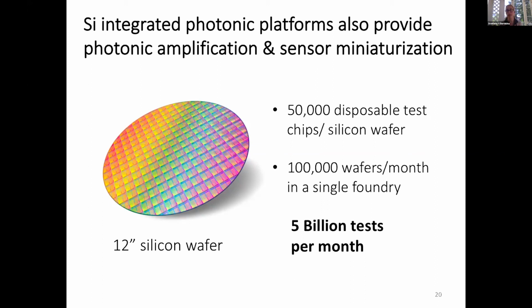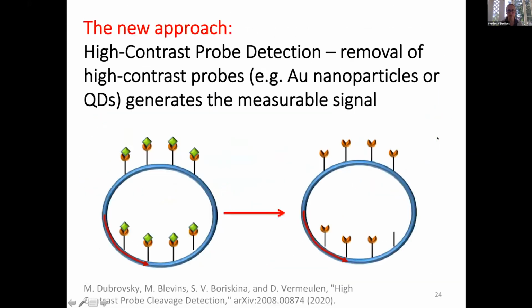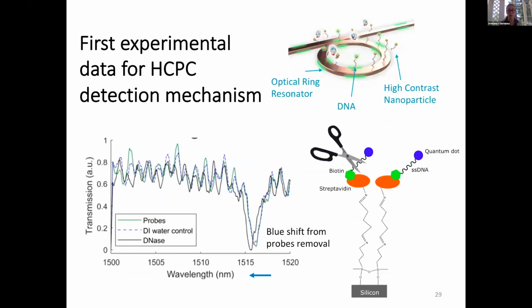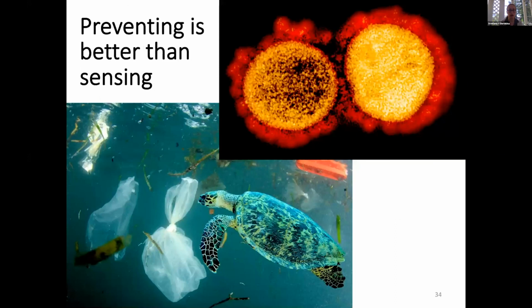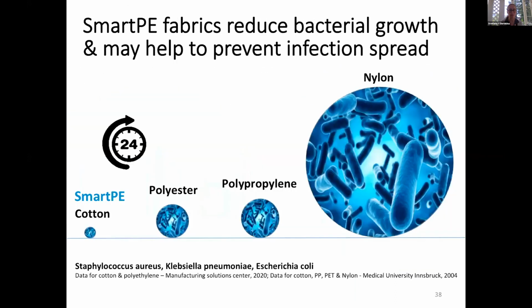And we measured it relative to other fabrics, and we were surprised to see how much slower is the bacterial growth. So this is a growth in 24 hours. And cotton is usually considered the best material because it has very little growth. But our recent testing showed that our material exhibits the same amount of growth as cotton, which is significantly smaller than everything else, which is very encouraging.